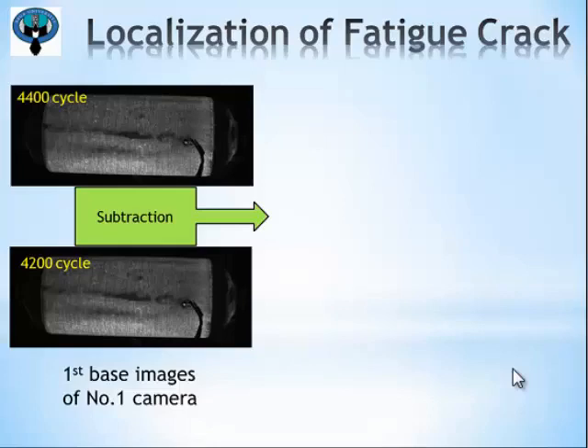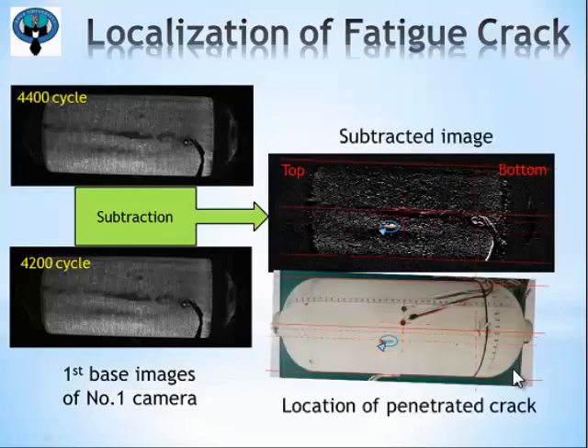Above image is the first base image of number 1 camera at 4400 cycles. After 200 cycles, a fatigue crack penetrated the vessel. Below image shows the first base image at 4200 cycles. Subtraction of above image minus below image shows the right one. As you can see, there is characteristic pattern at this location. This pattern means that the ML intensity decreases as same as the case of previous composite test piece.